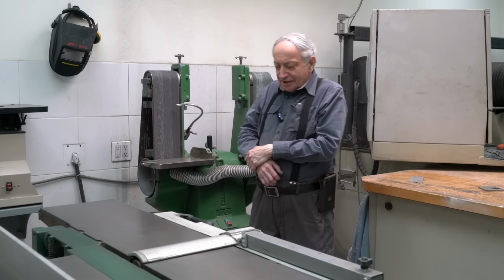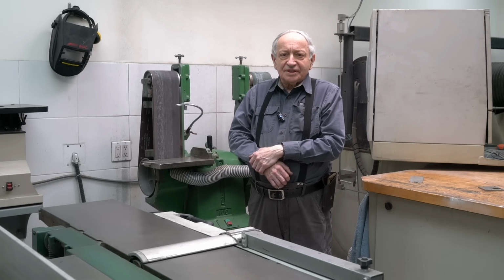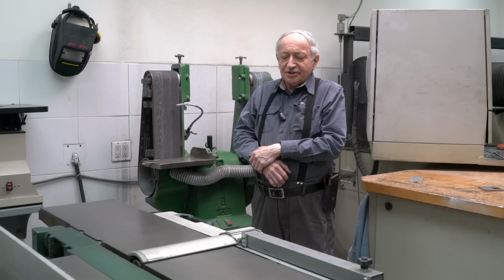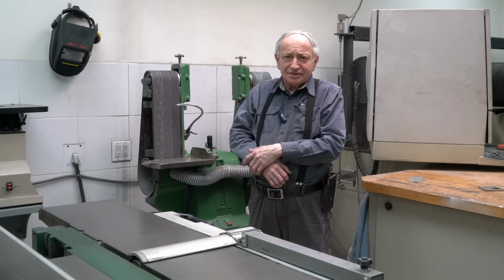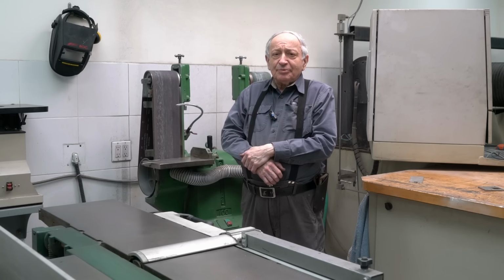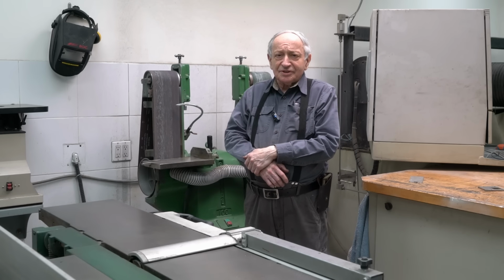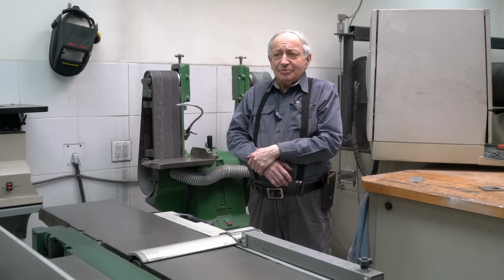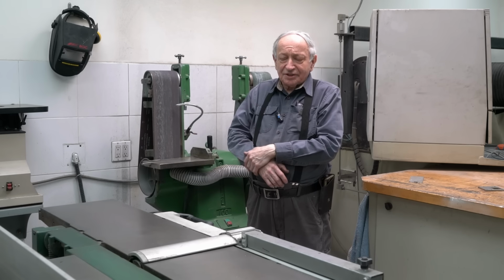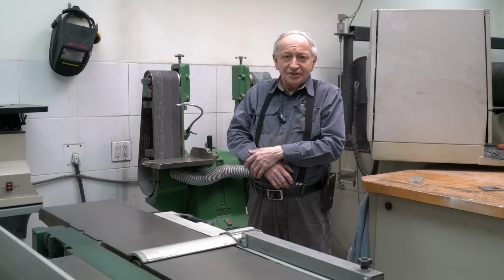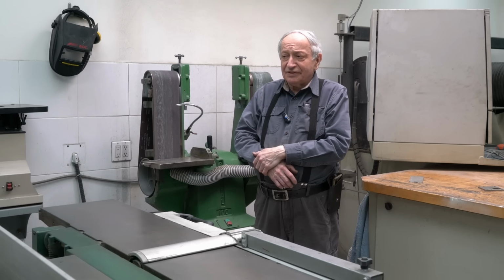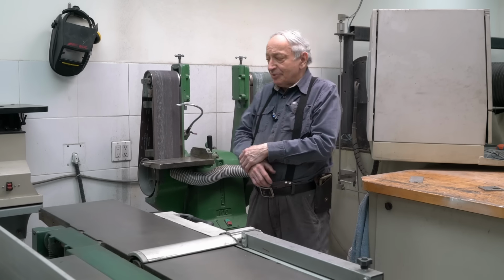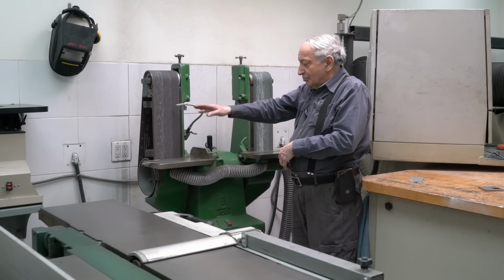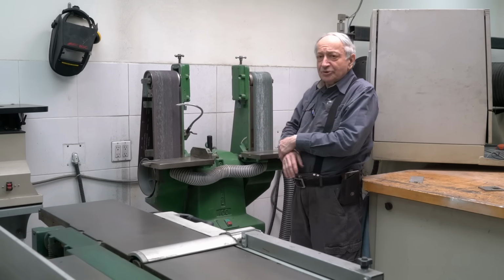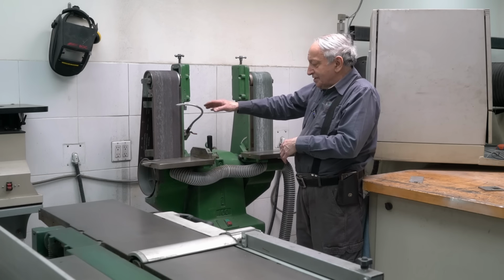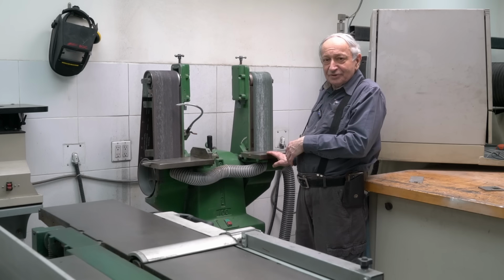Now, a question I'm asked often is, how do you protect things from rust? Especially in a situation where they can be exposed to water, mist, moisture, and so on. So the absolutely best way to protect things from rust, of course, is to electroless nickel plate them, because electroless nickel plating not only protects from rust, but it's harder than any steel. It's about Rockwell C70, so it never wears off. For example, on this sander, which has water spray, both tables were electroless nickel coated 25 years ago, and in spite of the abrasive, the coating survived 25 years of continuous use.